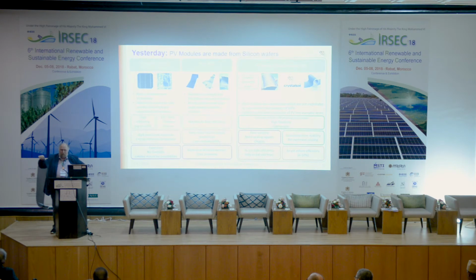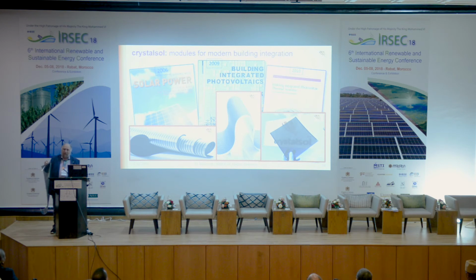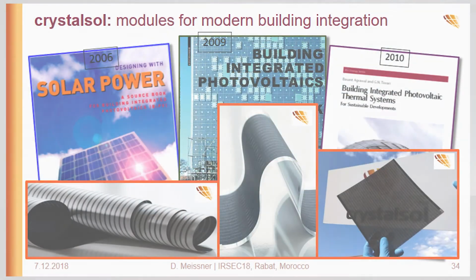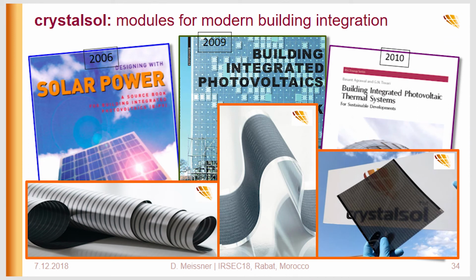So oxygen is not a problem here, but oxygen may well be a killer for organic solar cells. This is why actually I stopped with organic solar cells about 10 years ago, after having been the first one who really working with organic solar cells since 1988. At least if you don't count sensitization solar cell as organic. This has been done a little bit longer. Okay, so main application for us in the moment is building integration, because we can sell this stuff without sealing. This makes it much cheaper than all competitive materials.